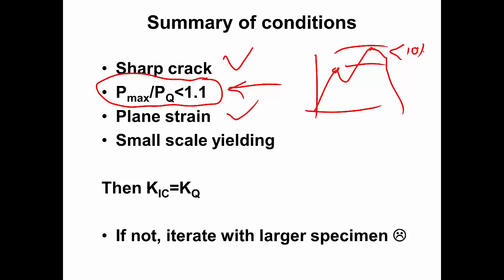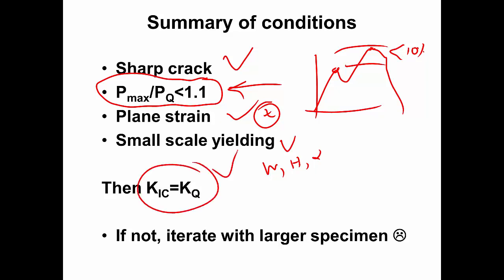Plane strain has to be satisfied. Small scale yielding has to be satisfied, and this puts a constraint on the thickness, and this puts a constraint on the overall dimensions of the specimen. As I said, if all these are satisfied, we got a number. If not, then we need a larger specimen. Larger either in thickness if plane strain is not satisfied, or in the overall dimensions of the specimen if small scale yielding is not satisfied. Or a better preparation of the specimen if some of the other conditions are violated. So it is a very tricky test that requires iterations if your initial measurements are coming from a specimen that does not really have the right size.